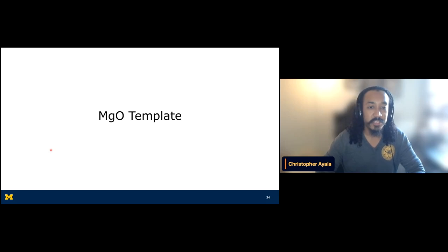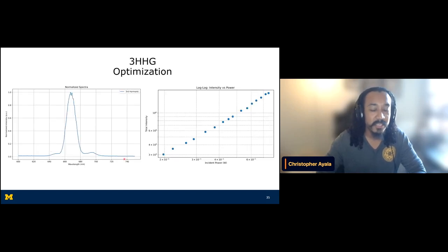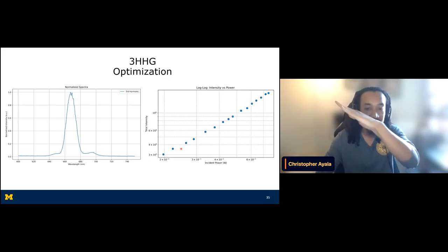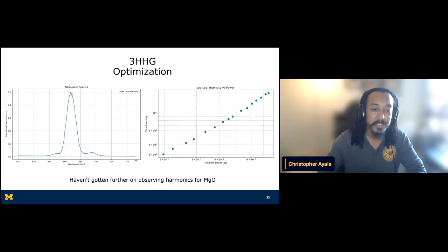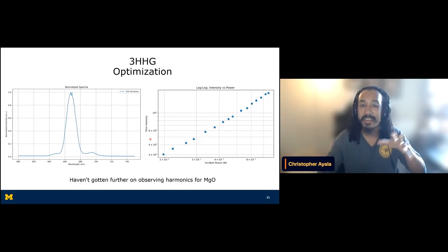So when jumping into talking about the MgO template, nothing super special can be seen so far. It's just that we have a peak shown at the third harmonic, and we have the power law relation that should follow an I to the 3 power law. The issue is that we just haven't done any more experiments on the magnesium oxide yet, and all my efforts have been pretty much put towards looking at the gallium nitride and optimizing to see if I can even get that last ninth order harmonic before we play around with the other samples.